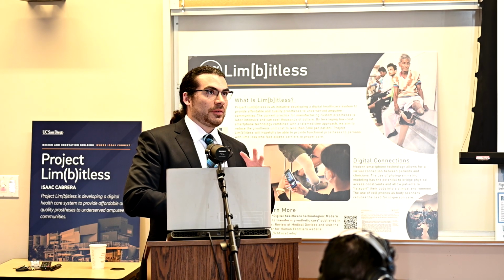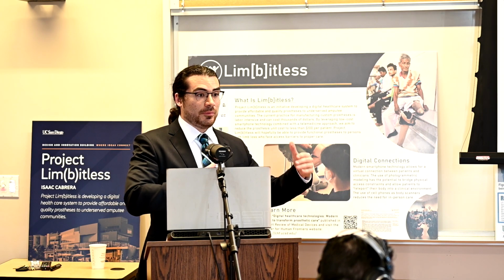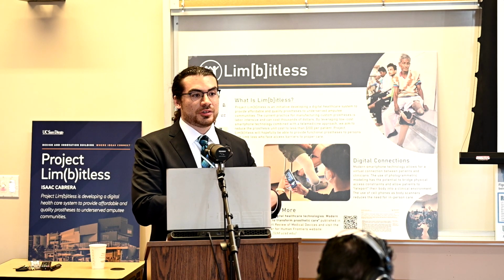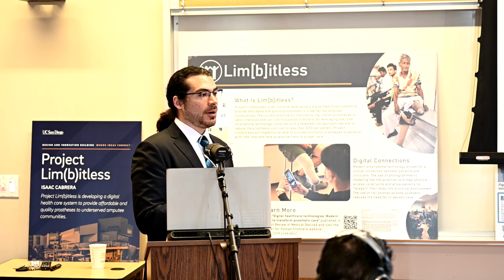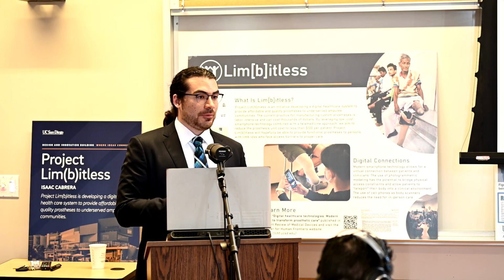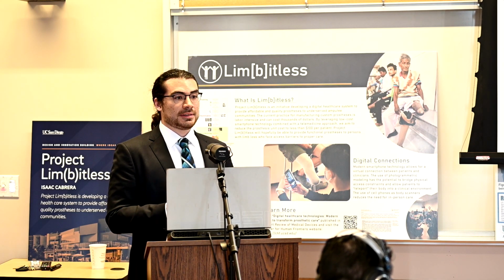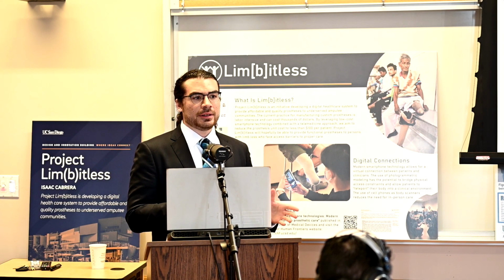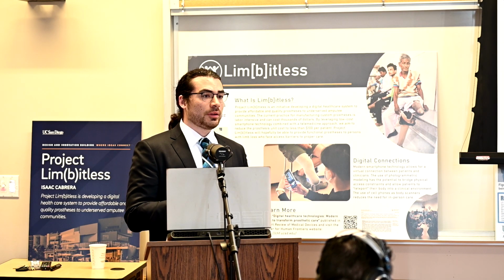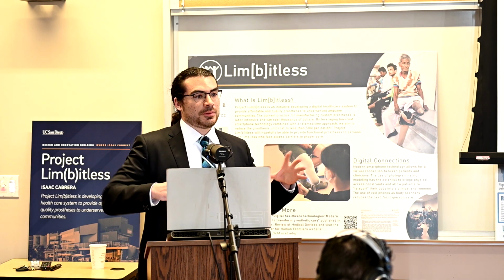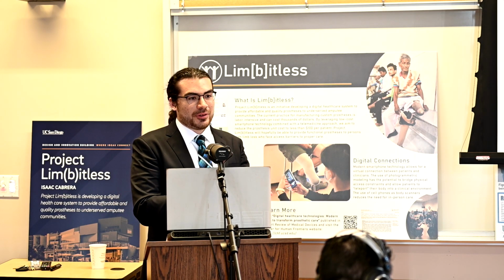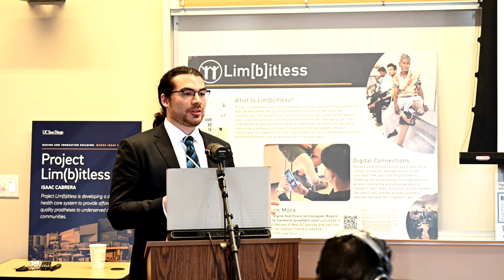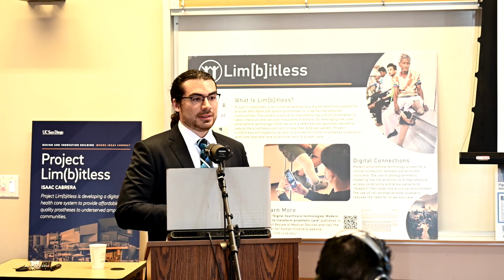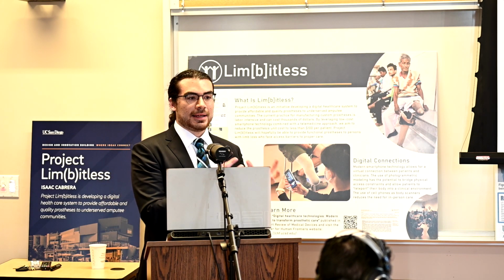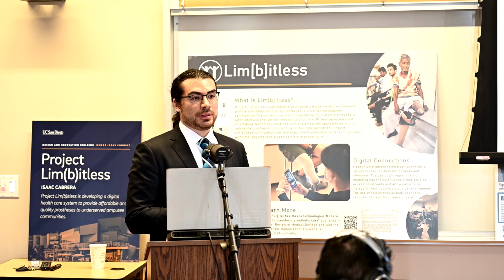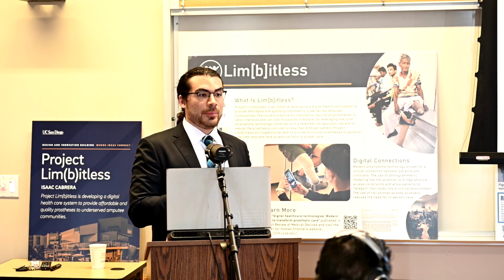But in terms of 3D printed prostheses, of course, ours are above and beyond where that technology is currently. And of course, not all prostheses that people wear are advanced composites. On our field expedition to India, we found out that all the prostheses they make in the Jaipur clinic are high-density polyethylene, and the tensile strength of that is actually quite low relative to what we were doing. So it's about the same. But how they addressed it is they just made them really fat, really thick, really heavy. So they're not optimized for strength to weight. But in terms of comparing to other plastic prosthetic sockets, they're pretty good. They're not exceptional, but they're better than the current standard.